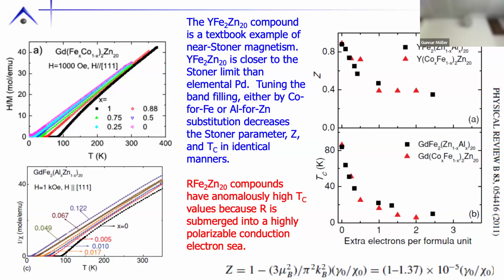And what's nice is, if you look at the yttrium, I can dilute with cobalt. I see that I drop out extra electrons per formula unit. I can also substitute zinc and aluminum. And again, I get the same drop. So this is beautiful band magnetism.